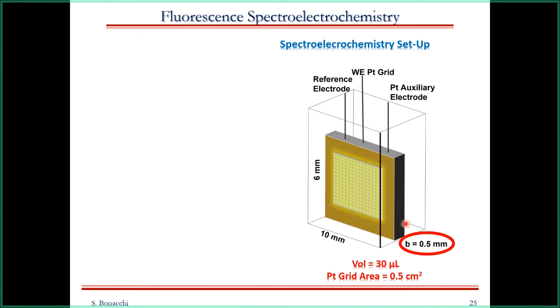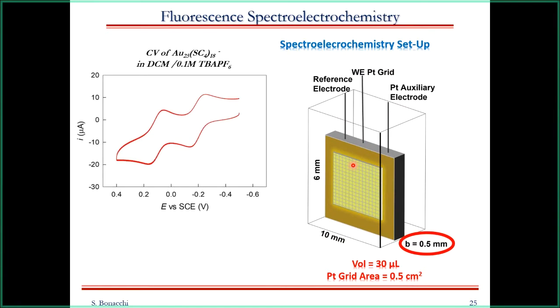spectroelectrochemical setup, which basically needs quartz cells. I would like to stress that we are using a very thin film active layer in order to minimize the diffusion layer in front of the working electrode, which was made of a platinum grid. And we use this setup to perform CVs, and here I report the CV of gold 25. It's a very nice CV that respects the electrochemical properties I showed you before.